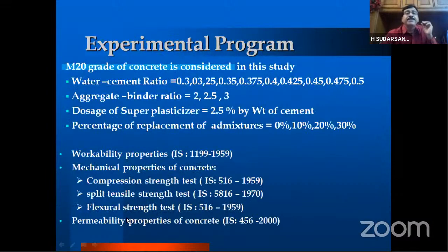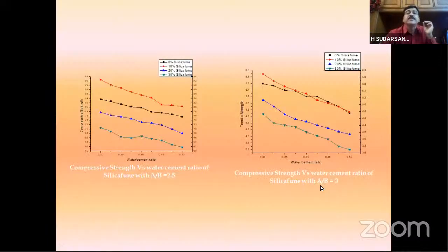These are the different parameters we have considered for the experimentation to derive the training examples for the network. The water cement ratios we have used are from 0.3 to 0.5. We used three aggregate binder ratios, 2, 2.5, and 3. We have used a fixed superplasticizer dosage, and replacements of cement with admixture at 10%, 20%, and 30%. We have used the workability properties as per IS 1199, the mechanical properties as compressive strength, split tensile strength, and flexural strength. The permeability properties by the chloride ion permeability test.